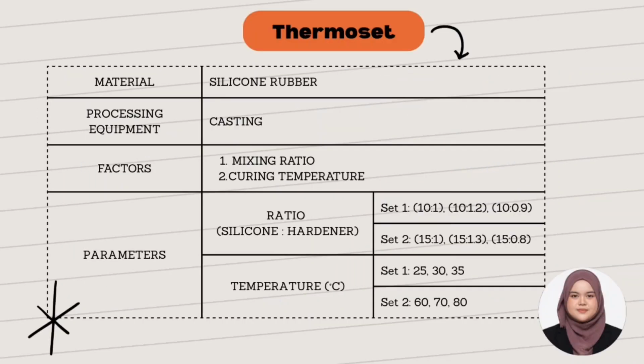Next, for the thermoset processing parameters, silicone rubber is used as the material, with casting as the processing method. Two main factors are considered, which are mixing ratio and curing temperature. For the mixing ratio, set 1 ranges around 10 to 1, while set 2 uses 15 to 1 with slight variations. Meanwhile, the curing temperature for set 1 is between 25 to 35 degrees Celsius, and for set 2, it ranges from 60 to 80 degrees Celsius.